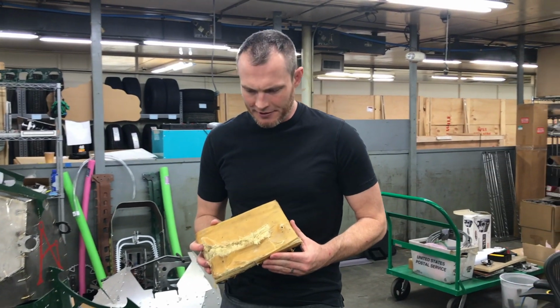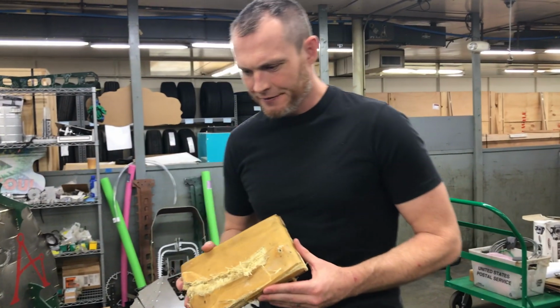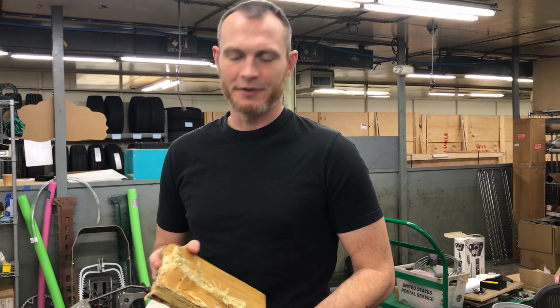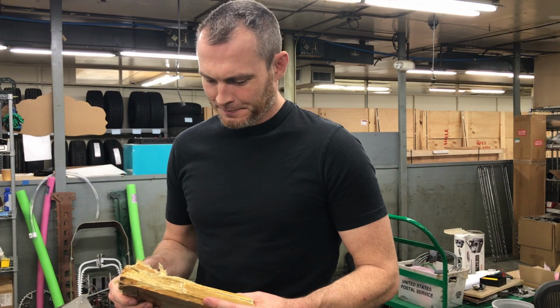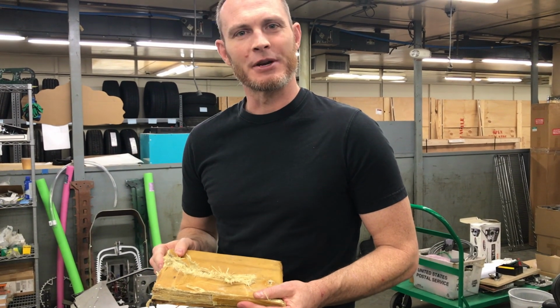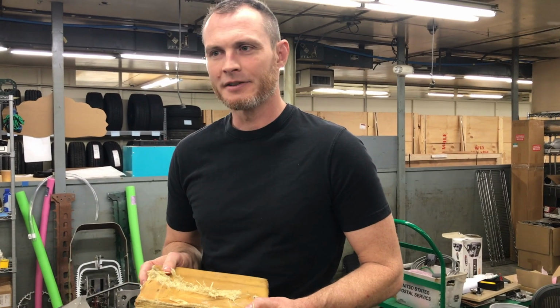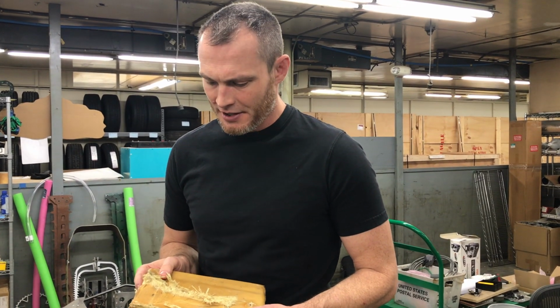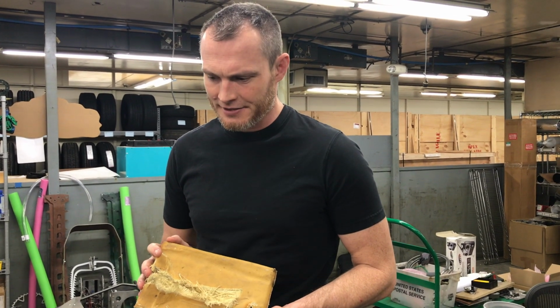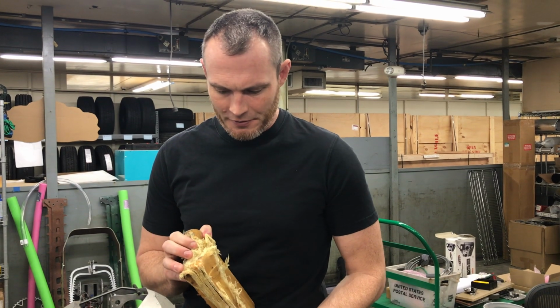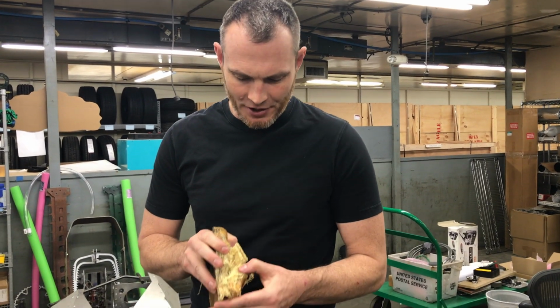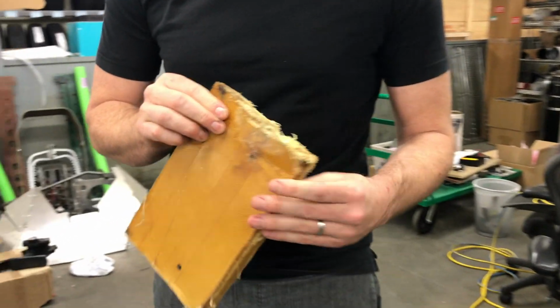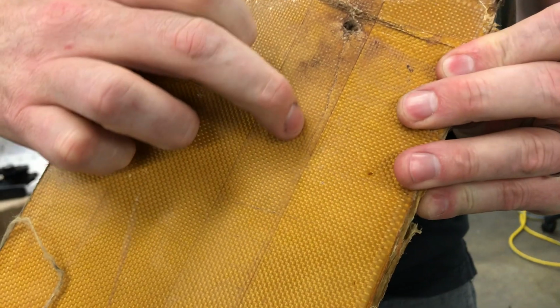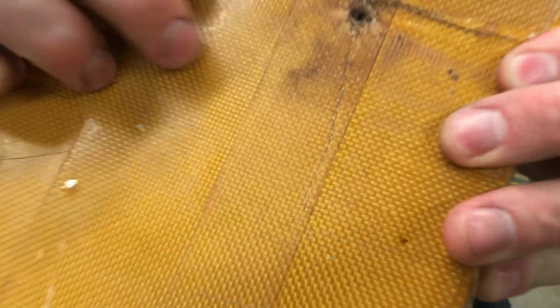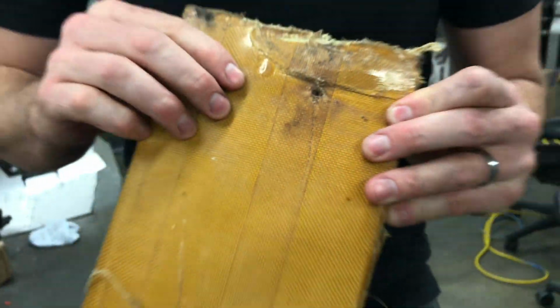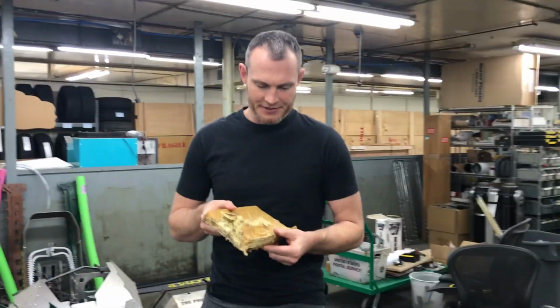So this is the result of the Kevlar test, and I think we've officially decided that the armor needs to be both tough and hard. And some of this might come down to how toughness is measured in the engineering world. The test that determines it does not use a cutting edge, it uses a blunt edge. And so even though this Kevlar, by the data sheet, has a similar toughness to the AR500, it was really destroyed by the test. The test article is cut almost all the way through. You can actually see failure on the other side of the test piece through 1 inch of armor, whereas the AR500 only probably experienced about 1/16 of an inch of penetration.